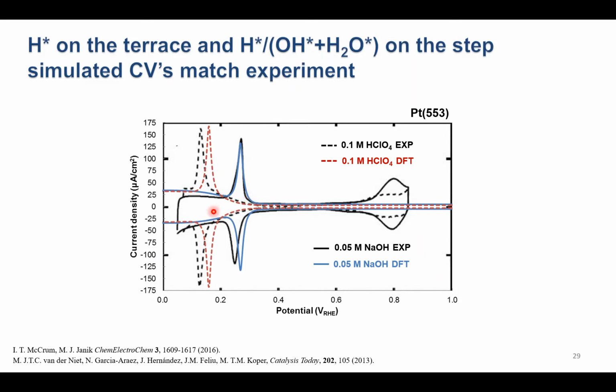But when we stick this cation close to the surface, because it retains most of its charge, that also generates a large surface normal electric field. And so we could ask, well, maybe this really was an electric field effect, and we've tricked ourselves by thinking it's a cation effect. And so this is where it's really nice to have additional insight from experiment.